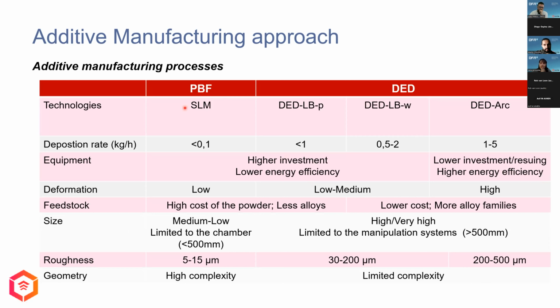Selective laser melting brings low roughness and high complexity of shape with low deformation in comparison with the other techniques. But also the deposition rates are lower. By contrast, direct energy deposition has higher deposition rates, but limiting the complexity and increasing the roughness and deformation. For that reason, it's usual to choose SLM for small parts that require higher complexity in geometry, and for bigger parts, the direct energy deposition.